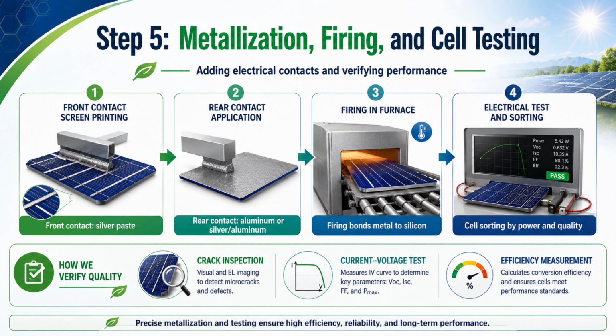After the wafer structure is prepared, the solar cell needs electrical contacts. These contacts collect the current generated inside the silicon and carry it out of the cell. The front side of the cell usually receives fine silver contact lines. These are often screen printed using silver paste. The silver lines must be conductive enough to collect current, but thin enough to avoid blocking too much sunlight. The rear side of the cell also receives a contact layer. Depending on the cell type, this may include aluminum, silver aluminum paste, or other metal structures.